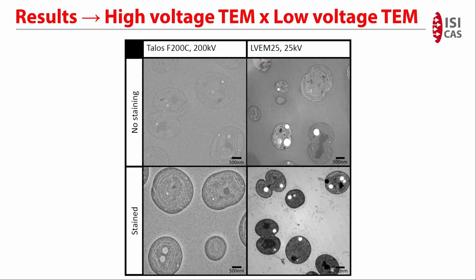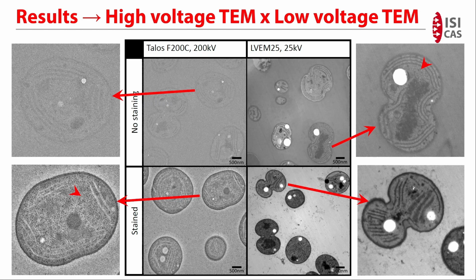For the TEM imaging, we studied both stained and unstained samples using either a 200 kV or 25 kV electron beam. As expected, stained samples imaged using 200 kV provided us with nice contrast and resolution. However, samples stained only by osmium tetroxide in the freeze substitution medium were almost invisible, and some of the structures seen in the stained samples are indistinguishable. Nevertheless, the unstained samples imaged by the 25 kV beam gave us sufficient contrast, quite comparable with stained samples imaged by a high-voltage transmission electron microscope. Unfortunately, stained samples imaged at 25 kV were in some cases, on the contrary, too dark to recognize all of the structures in the cells.